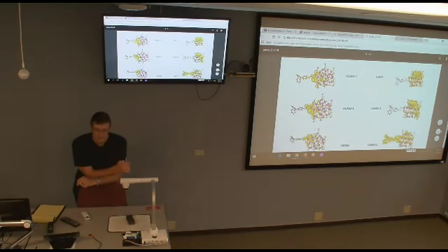So I don't know if that's just an artifact of the calculation, but if the dye comes in that direction, it means this happens and it's definitely not stable, right? Or maybe you have this over strong effect because you don't have solvent. Maybe in the presence of solvent, this effect, it cannot come too close. And maybe it will be softening and you will not really break your molecule.